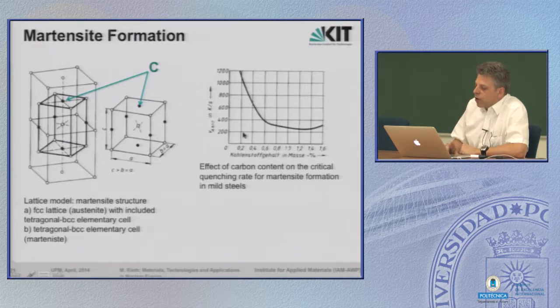Depending on the carbon content, it needs more or less quenching rates. I have already told you. Around 1% carbon content, it's rather easy to produce such martensite structured lattices. Well, you need a bit more than 200 Kelvin per second. That's quite easy to handle.